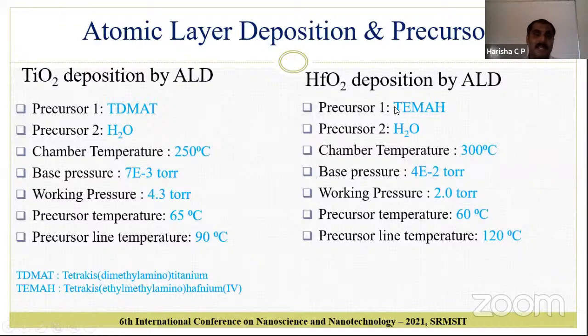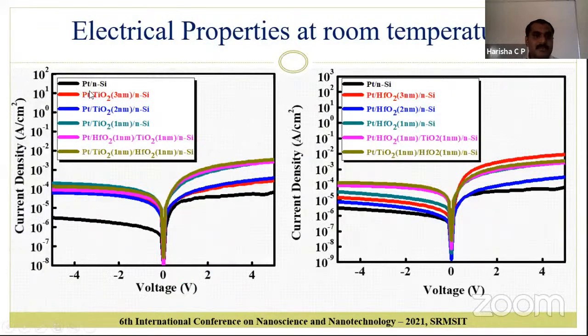By inserting a thin dielectric layer, you can see the first curve, the black curve, is platinum on N-type silicon. This is an MS structure, a metal semiconductor structure, where you can see an asymmetric nature. That means there is a higher forward current and lower reverse current. This shows that there is a Schottky barrier between the metal and semiconductor. By inserting thin layers of titanium oxide of 3 nanometer, 2 nanometer, and 1 nanometer, and also a bilayer of TiO2 1 nanometer and HfO2 1 nanometer,